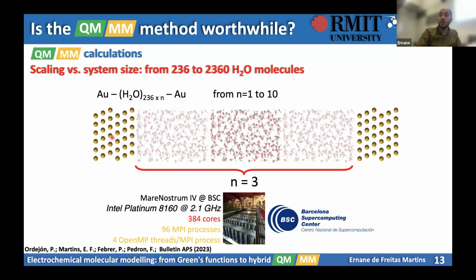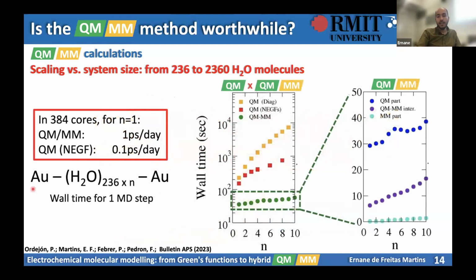So considering this gold electrode, so gold on one side, gold on the other side, in the QM part, we increased the amount of classical water in the center. So this is an example of 3 units, let's say. So we have here 1, 2, and 3 units of water. In total, 1 unit has 236 water molecules, and then we increase this up to 10. That means a total number of atoms of nearly 8,000 atoms. And then we tested the performance of this in this architecture here.